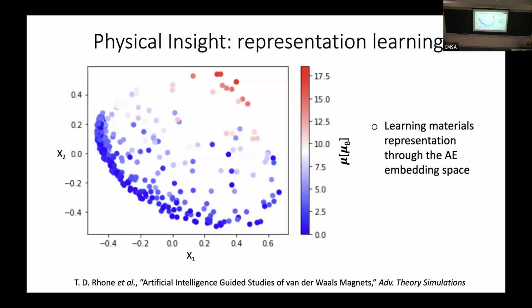So you can imagine if you had, say, a variational autoencoder set up to do generative modeling, you go to this part of the space and then decode what that material should be and find another material with a really big magnetic moment potentially. We haven't done it yet, but that's an idea for the future. But the point is, the model here is learning the structure-property relationships. Clearly, the structure is encoded in the input, which is then somehow encoded in latent space. And you project it to 2 dimensions. You can extract a mapping between the structure, some transformation of the structure, to the magnetic properties, which is kind of interesting. It's hard to get physical insight from this particular approach, but there are ways you can maybe massage this to get some insight from it.